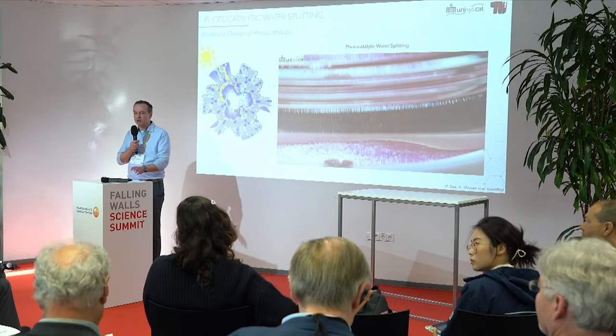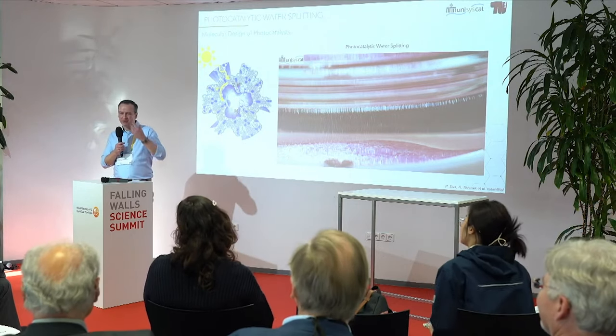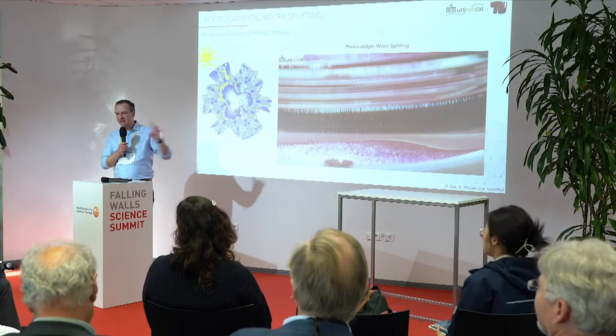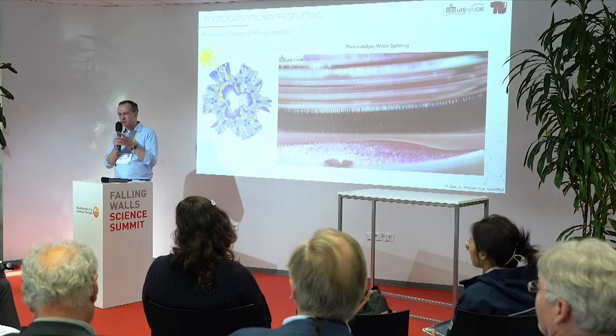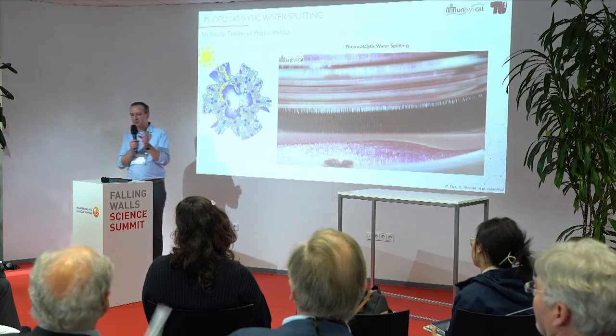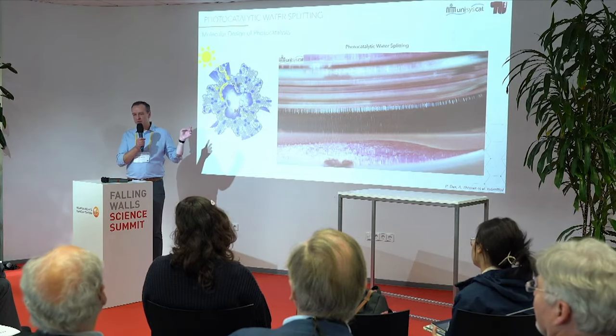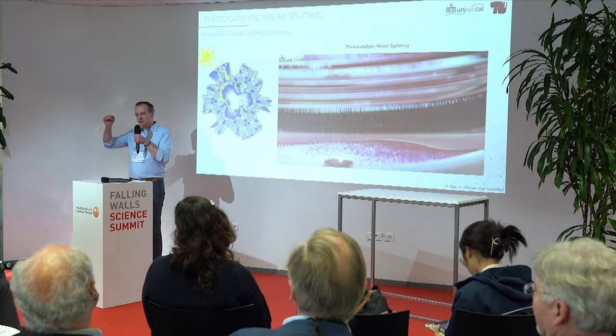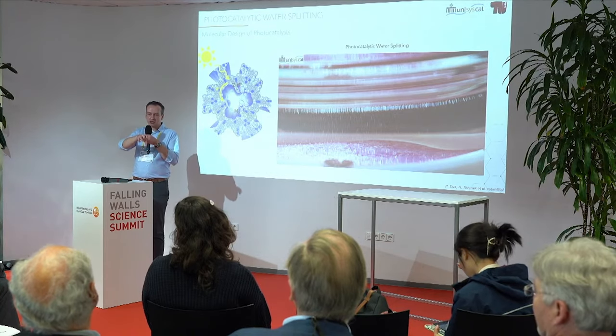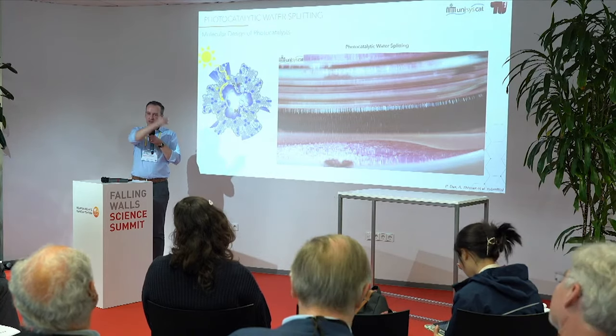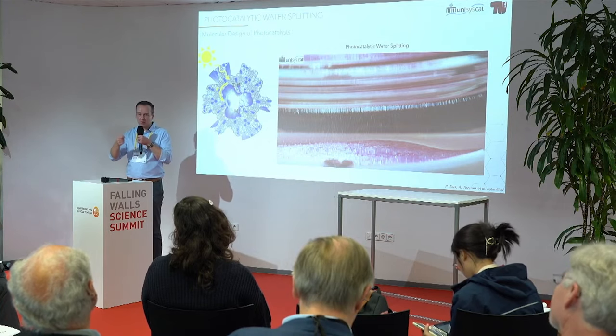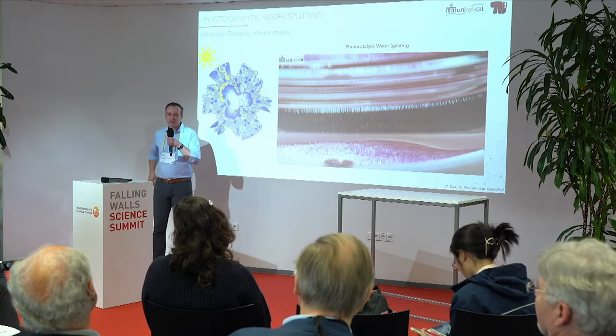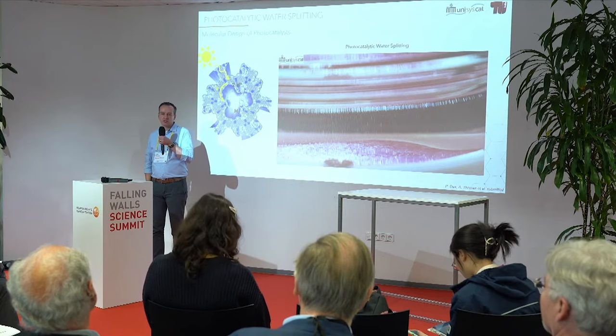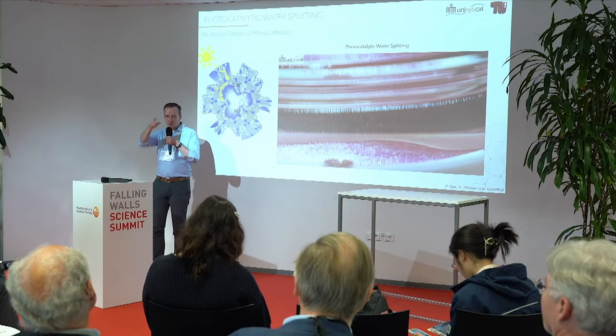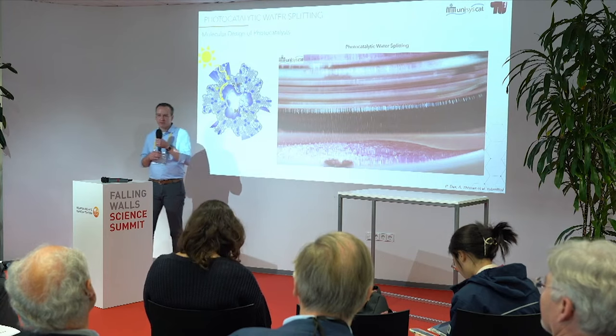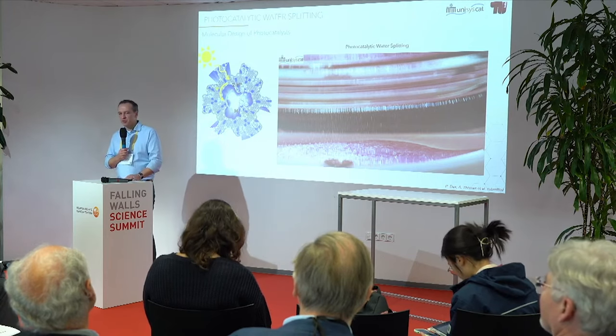Wow, this is now a pro question, let's say. Because, of course, you make bubbles of hydrogen, you make gases which have to escape these very small pores, which are just 1 nanometer in size. This is a lot of overpotential which is happening there. We have seen, actually, when we make hierarchical structures, which means we introduce larger pores of micrometers into these microporous materials, which we can do by templating approaches, then we increase the efficiency by a factor of 3 or 4 to avoid the overpotential by bubble formation. That's a very interesting point, yeah.